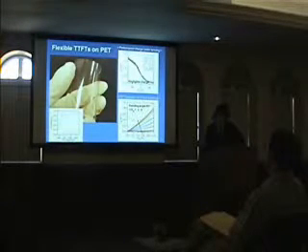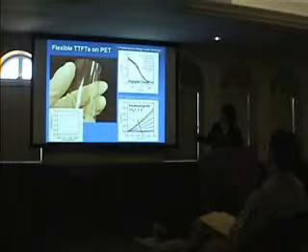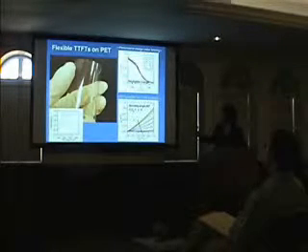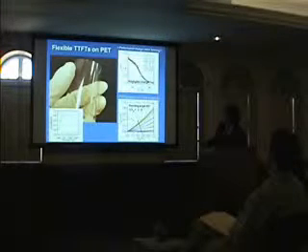Gold has a higher work function than ITO, so it can form a more ohmic contact to the carbon nanotube valence band. Using the same method, we have fabricated devices on a flexible substrate — here is a PET substrate with a bunch of devices. We characterized the devices under bending, and shown here is a transistor measurement of a device at different bending angles. You can see that the device showed negligible change in performance under bending. We were also able to operate the device as a transistor on a substrate bent by 90 degrees.